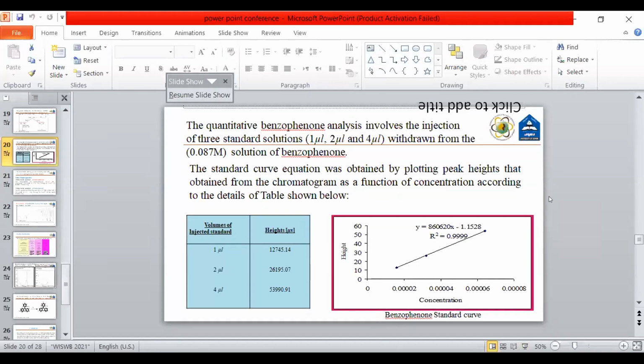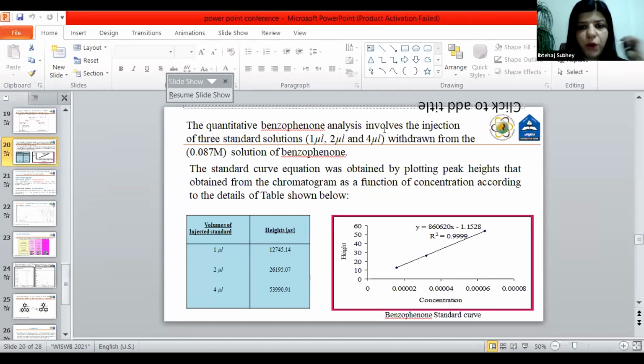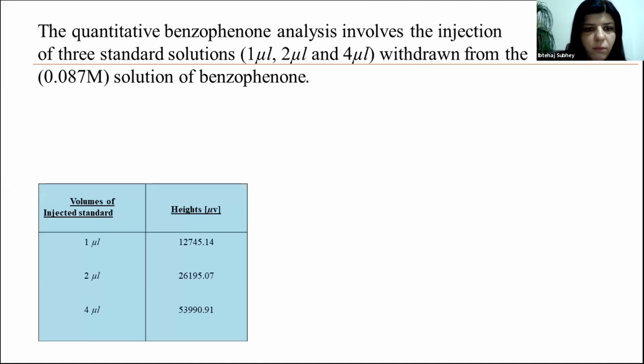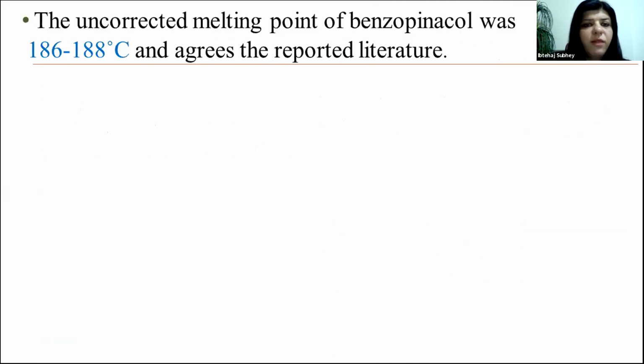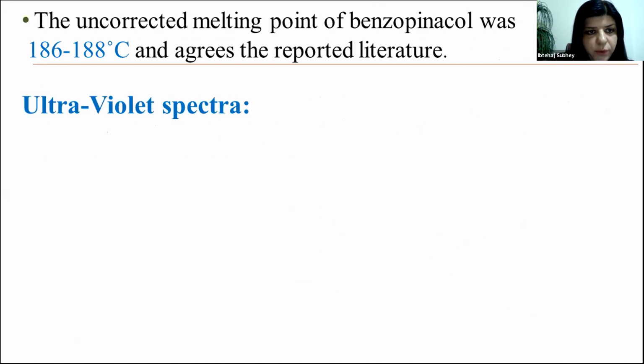Okay, it's back. The quantitative benzophenone analysis involved the injection of 3 standard solutions, 1, 2, and 4 microliters withdrawn from a 0.087 molar solution of benzophenone. And this figure shows the benzophenone standard curve, R squared closest to 1. The standard curve equation was obtained by plotting peak height obtained from the chromatogram as a function of concentration. The uncorrected melting point for benzopinacol is about 186 to 188 centigrade and agrees with the literature reported.